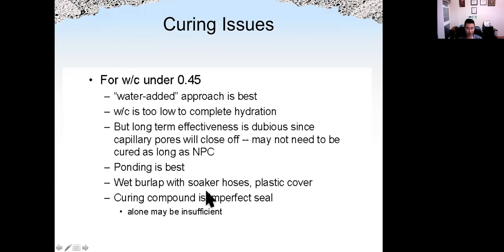For curing issues, for water cement ratio lower than 0.45, putting more water is the best, or the water-added approach. Because for concrete with lower water cement ratio, we better provide more water to the system, to ensure it doesn't have too much shrinkage, and the water cement ratio is too low to complete the hydration.